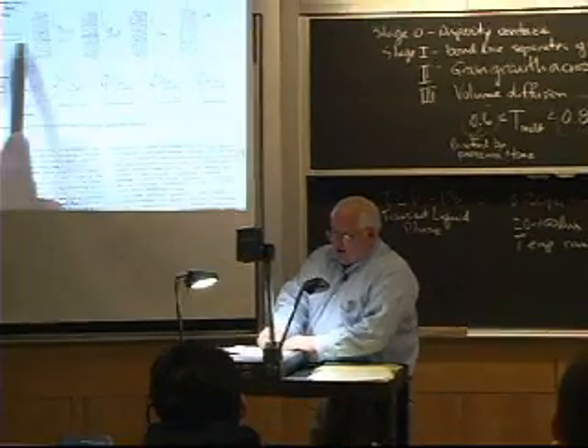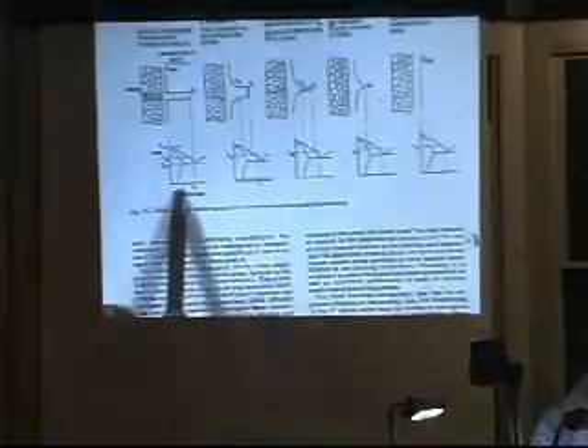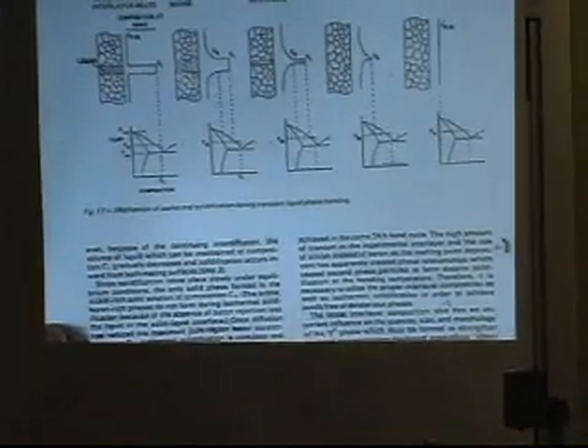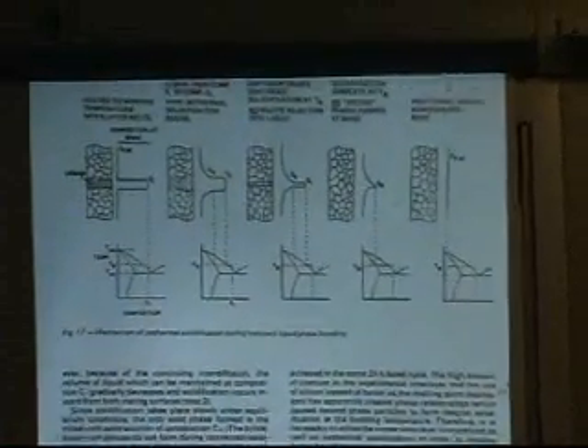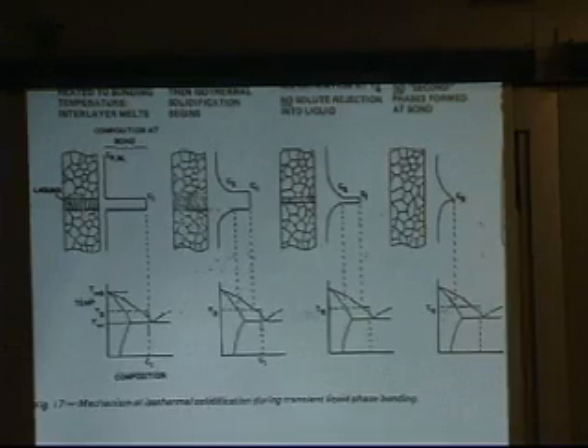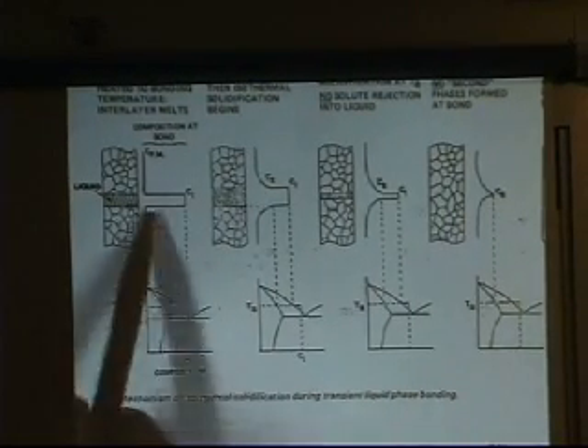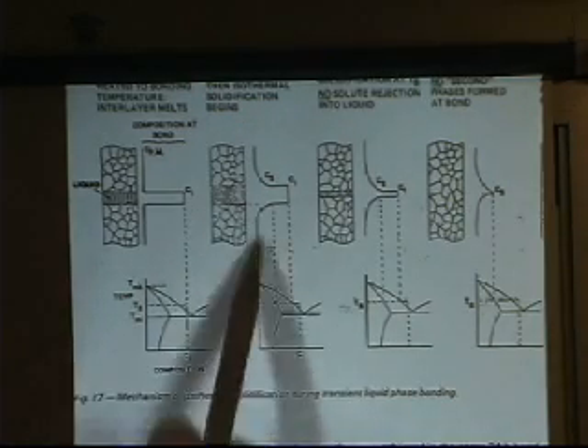But basically, what happens is I've got this liquid layer which has a high concentration, in this case of boron, and this is what the nickel boron phase diagram looks like. Let's get in a little closer here. You can do this in lots of systems, not just nickel boron. High concentration of boron, and I hold it at temperature for a long time, and it's isothermal solidification.